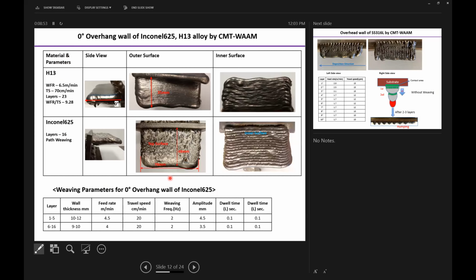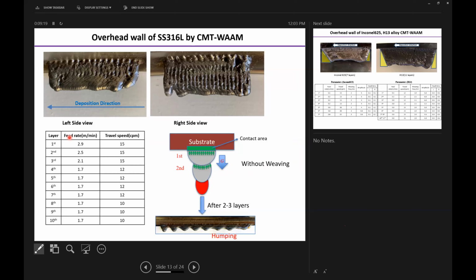Then we deposited the 0-degree overhang wall of the H13 alloy with the wire feed to travel speed ratio of 9.28. And for depositing the overhang wall of Inconel 625, we used the weaving tool path because we were not able to deposit with the regular tool path.